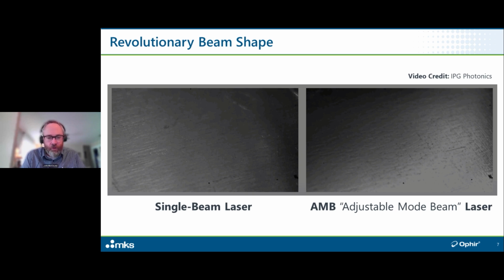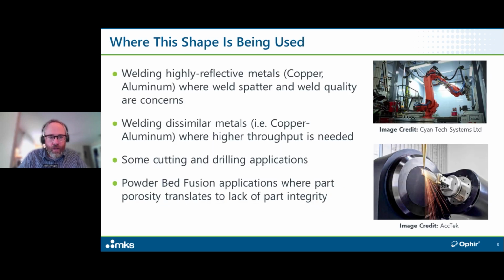And the end result is just an aesthetically not pleasing weld, versus what they call the adjustable mode beam laser, or the AMB laser. Very stable keyhole, very stable weld. So that's the kind of result that you can expect from utilizing this beam shape. All right, so where is this beam shape being used?